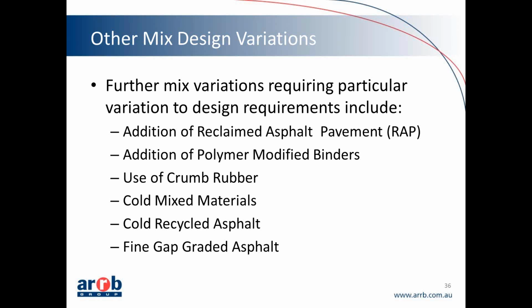A little bit of advice on cold recycled asphalt, which is to take the reclaimed asphalt pavement, mix it with some fresh foam bitumen binder or emulsion binder and put it down as a base material. And also we haven't entirely discarded discussion on fine gap graded asphalt, which is another variation of asphalt suitable for lightly trafficked applications where you want a nice smooth finish and a very workable mix that can be compacted to make a good durable asphalt. So there's a little bit on each of those materials in the guide, and if people want to ask questions we can answer them.